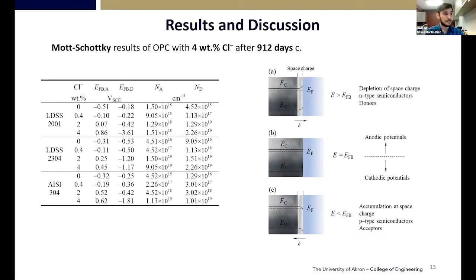The carrier density for the acceptor and donor constantly increased with the chloride content, which is seen in the literature. However, the acceptor of the lean duplex was the lowest of all 3, showing its outstanding corrosion protection.